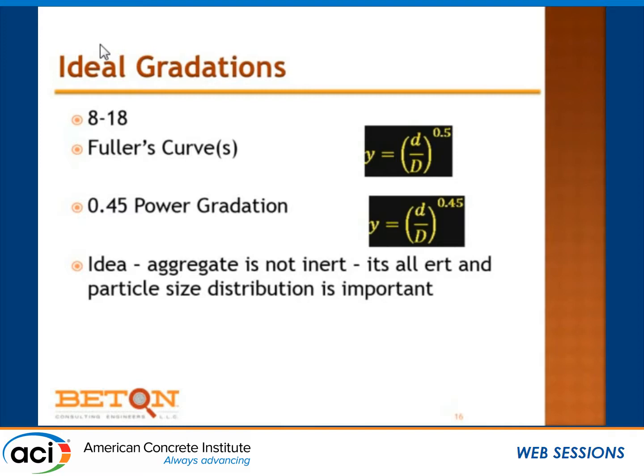Other than that, these may or may not give you the maximum density. But the concept is the right one, which is that the aggregate is not inert, right? It's all ert. The particle size distribution is important. But the particle size distribution is important to who mainly? The installer. It doesn't matter, so long as you have the concrete hardened properties set properly, what the aggregate gradation was, or for that matter, what the slump was.